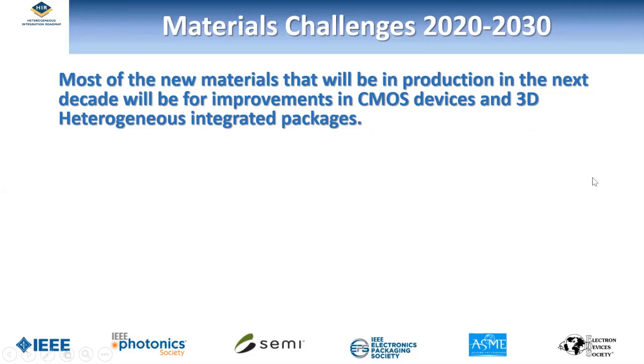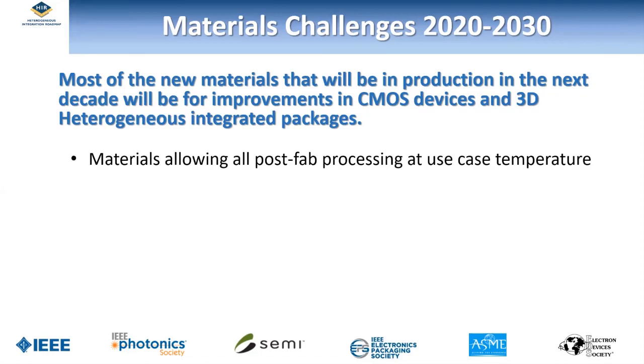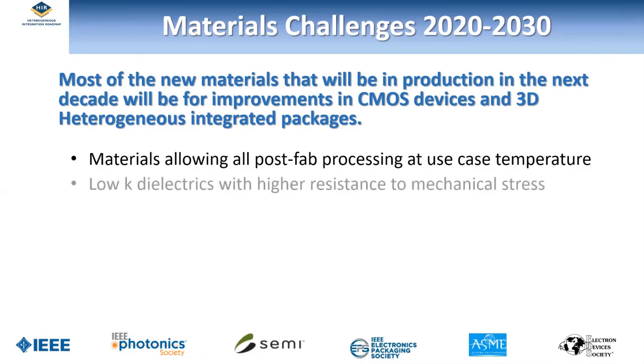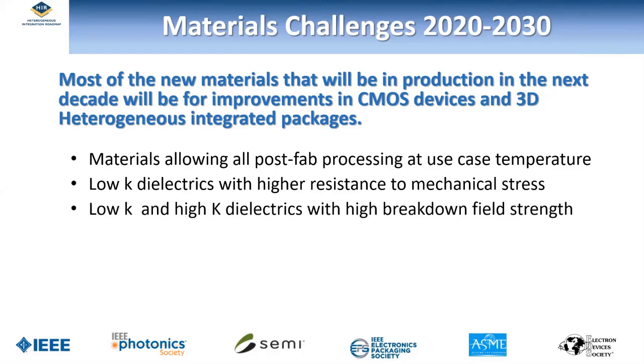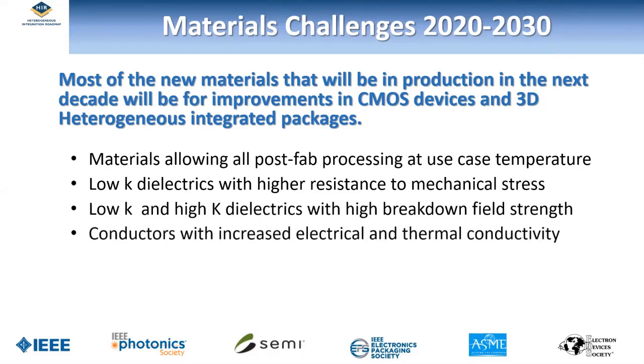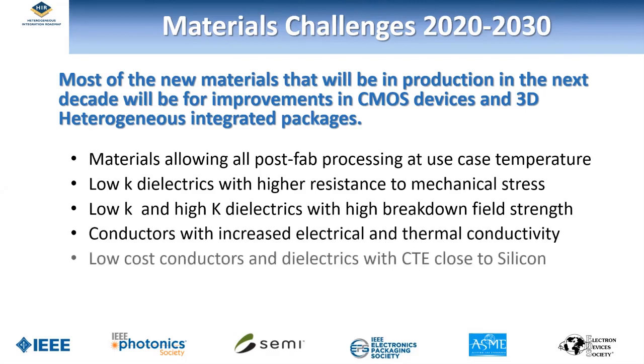Okay, most of the new materials that will be in production in the next decade are for improvements in CMOS and to support 3D integration. Materials allowing for all post-fab processes at use case temperature. That's certainly important because you don't want the properties to change by inserting a lot of stress by operating at a different temperature from which you put them together. We have to have lower K dielectrics with higher resistance to mechanical stress. We have to have low and high K dielectrics, both with high breakdown field strength. We have to have conductors with increased electrical and thermal conductivity better than we have today, and low cost conductors and dielectrics with a CTE very close to silicon in order to manage the warpage problem.